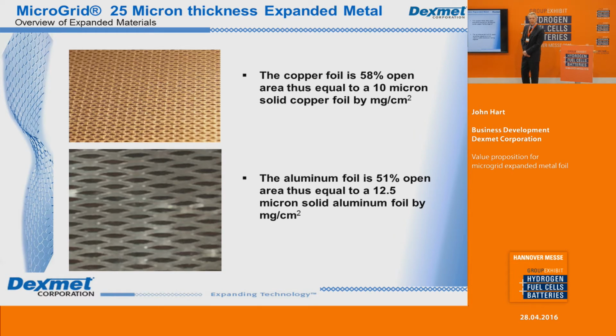Now, for lithium-ion batteries, we've been in development for the past 5 years developing the micro tooling so that we could get down to where we could create this kind of foil on a 25 micron. And so we've developed samples where the copper foil at 25 micron is 58% open area, which is the weight equivalent to a 10 micron solid copper foil, which is the industry standard. On the aluminum side, we've made samples of 51% open area, which has the consistent weight burden that you would get from a 12.5 micron aluminum, which again is consistent with industry standard. And if you're interested, we have plenty of samples right behind you at the booth there.